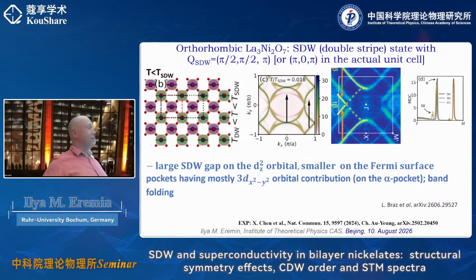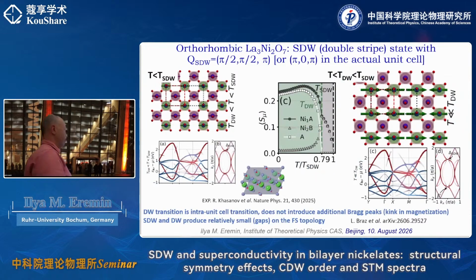Okay, so that's our kind of discussion with Damascelli, because Damascelli has a very exotic explanation for his data. Anyway, but now they continue to lower the temperature and allow for charge order to develop. And there you see that there is another order which develops, because it turns out that this double stripe is energetically unstable towards forming an additional intra-unit cell charge density wave order.